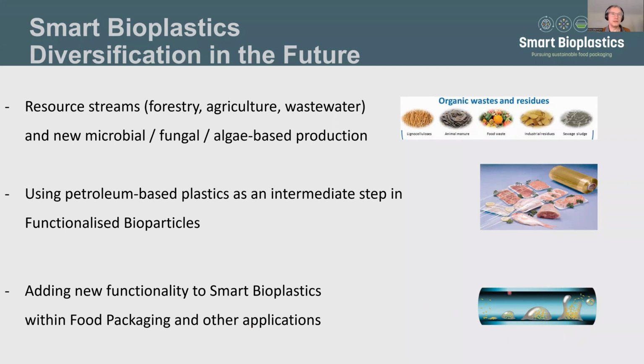but we could also use, and I'll just show this here, for example, biofilms in meat, fish, or dairy production plants, where metal surfaces and pipings are often inaccessible for thorough cleaning and provide ample ground for bacterial contamination and then biofilm formation. And it is very hard to get rid of those biofilms, even with harsh chemical treatments that are very aggressive to the environment and to the workers that have to apply them. And if we could use functionalized bioparticles, for example, that degrade those biofilms and then kill the bacteria that are harbored and protected in there,